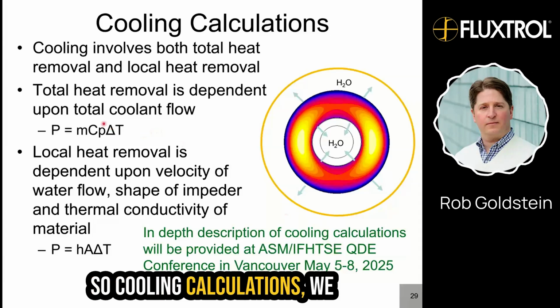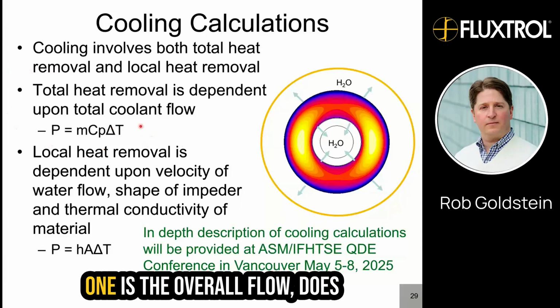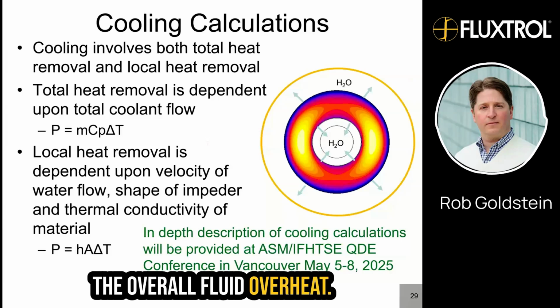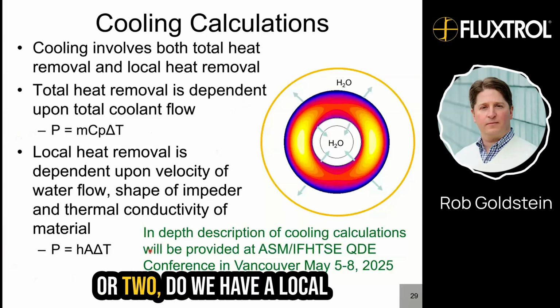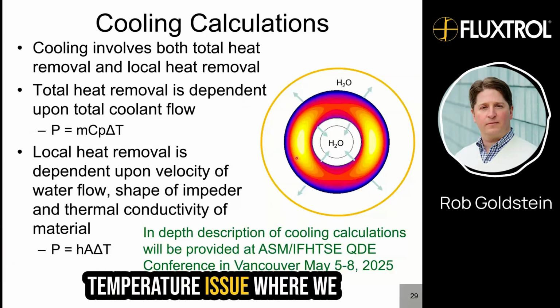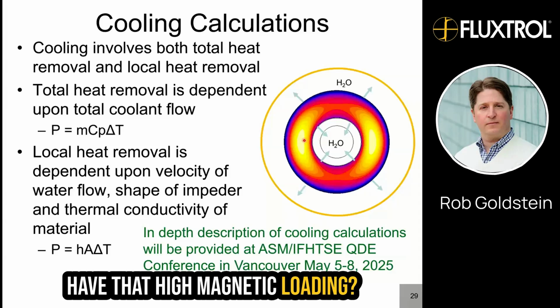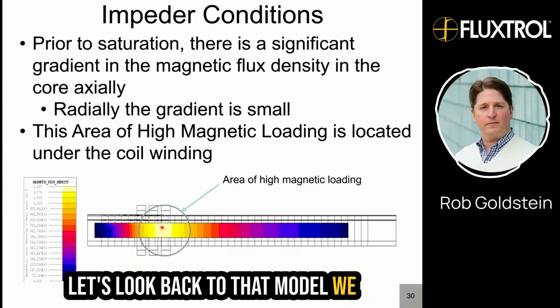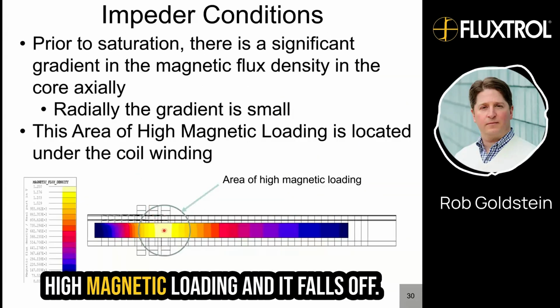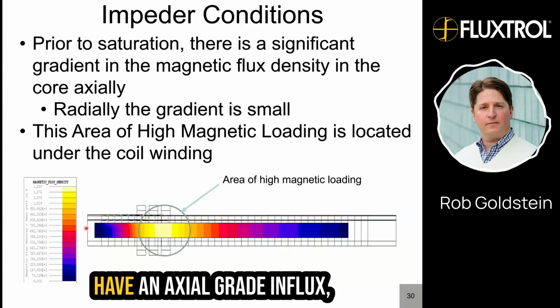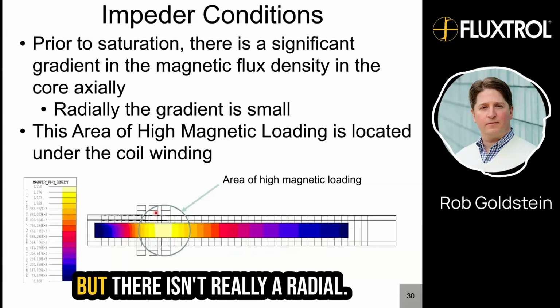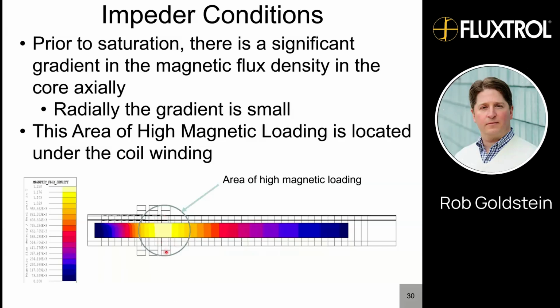So cooling calculations, we look at two different things. One is the overall flow. Does the overall fluid overheat? Or two, do we have a local temperature issue where we have that high magnetic loading? Let's look back to that model we showed earlier, and we've got our area of high magnetic loading, and it falls off. So what we see is mainly we have an axial gradient in flux, but there isn't really a radial one.